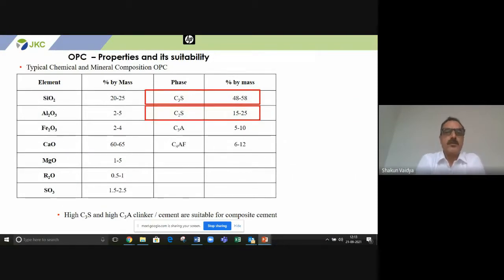So OPC properties and its suitability. In ordinary Portland cement, the compounds C3S and C2S should be around 48 to 58% and 15 to 25%. These are the major two compounds which enable the cement to gain strength: C3S for early strength from 1 to 7 days, and C2S from 7 days and beyond up to 28 days. So high C3S and high C3A clinker cements are ideally suitable for blended cements, especially composite cement.